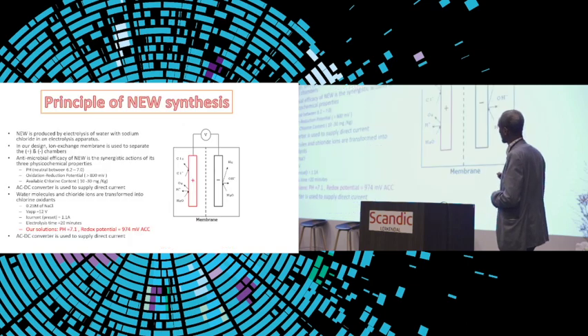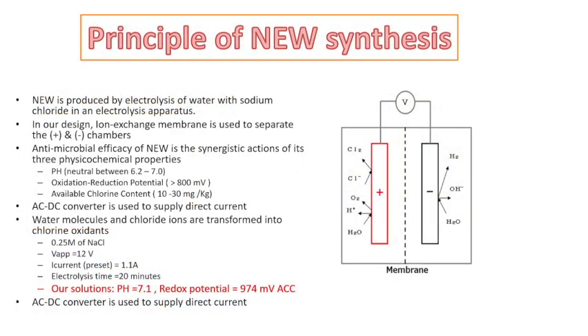And this is at some stage, and through funding, if we get funding, we are about to realize the device instrumentation aspect. The synthesis follows, as I said earlier, very simply. There is an ion exchange membrane. We start with 0.25 molar sodium chloride, and we apply a direct DC voltage of 12 volts and a current of 1.1 amperes. We did the electrolysis for 20 minutes, and our solution had a pH of 7.1 and a redox potential of 974 millivolts.